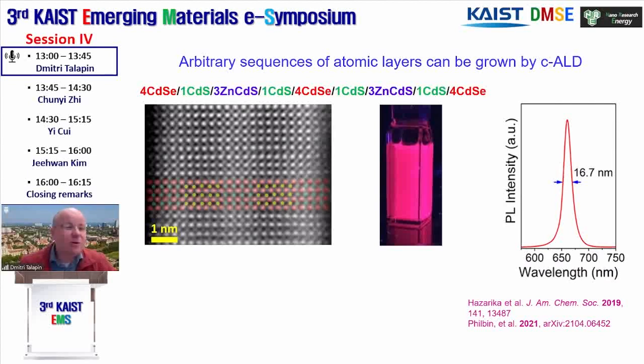So it's pretty close to molecular beam epitaxy, but now in solution. And we can do it in parallel on a huge number of nanostructures in solution by doing colloidal atomic layer deposition, and we do not introduce inhomogeneous broadening. When we claim that we grow one layer at a time, we did a lot of experimental studies, spectroscopic studies, to validate that it is very close to reality.